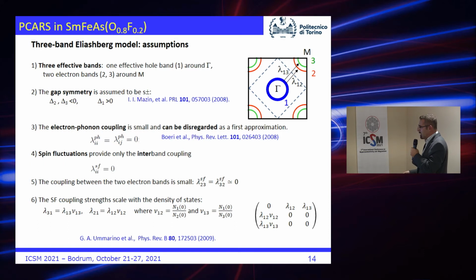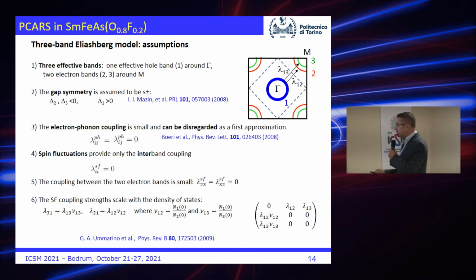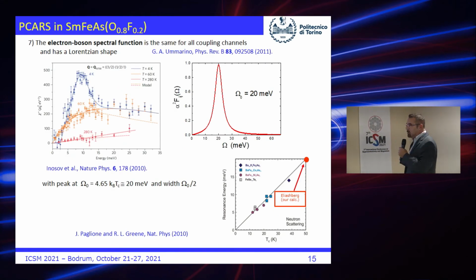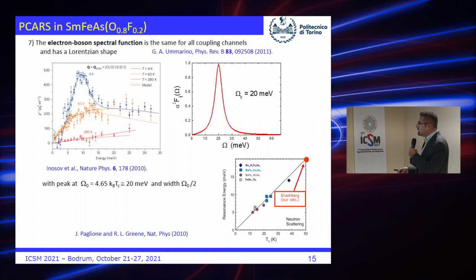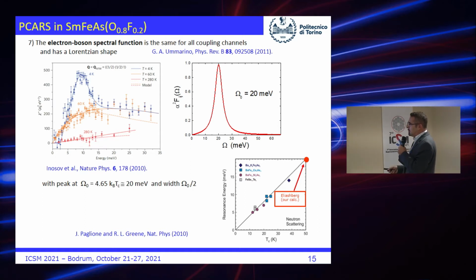And in principle, I should have lambda 2,1 and lambda 3,1 that are actually connected to these through the ratio of the density of states of the bands. Then, what about the spectrum of the boson? We know that from measurements of inelastic neutron scattering, the chi double-prime, that means the imaginary part of the spin susceptibility, has a peak that has this shape in the normal state.